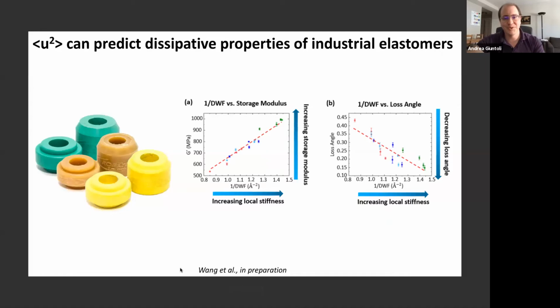And this is what we did recently in a collaboration with industrial partners. In particular here, the person working on this project was Ao Wang, a PhD student in our group, who simulated a specific model for elastomers, finding that the Debye-Waller factor was correlating with the storage modulus and the loss angle for these systems when changing the chemistry. So that was a guide to see what was the effect of the chemistry on these mechanical and dissipative properties of these industrial elastomers.